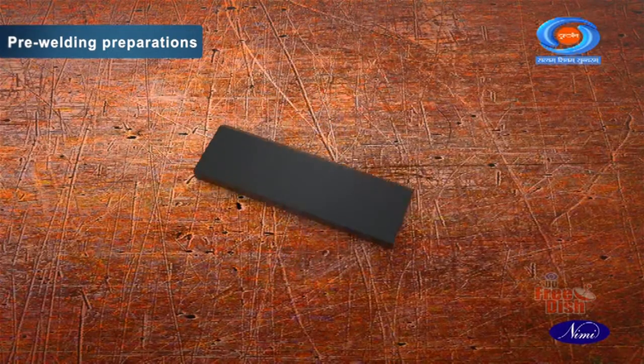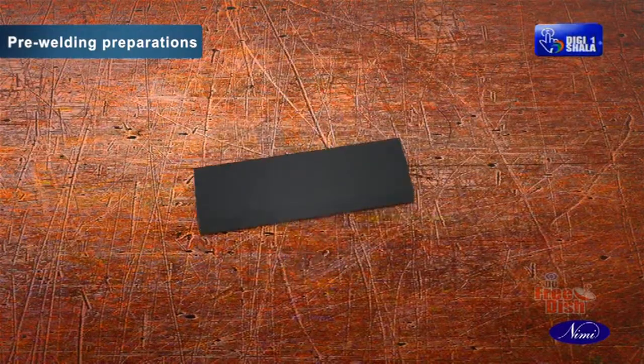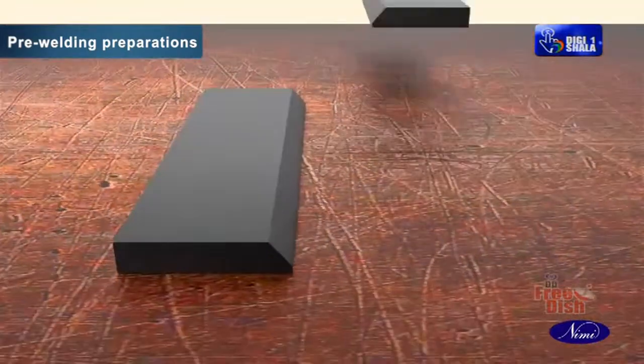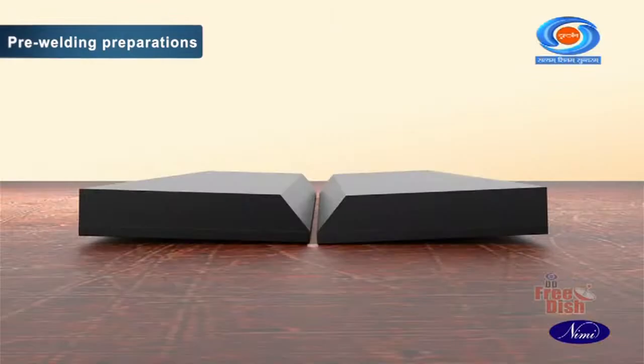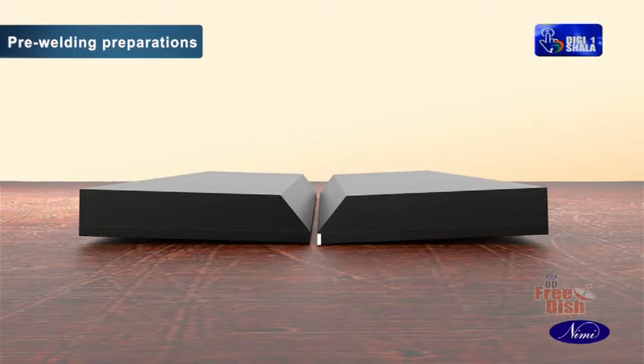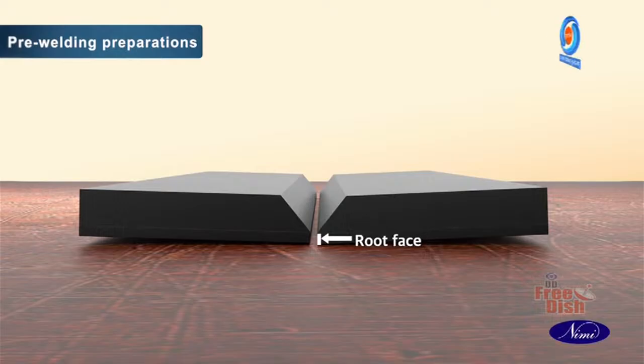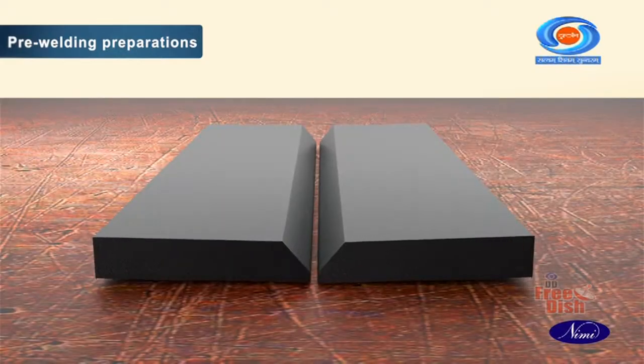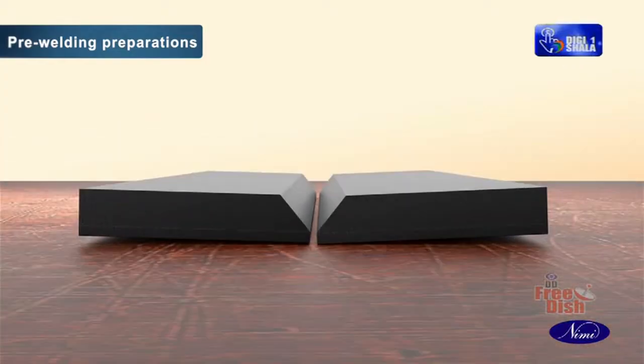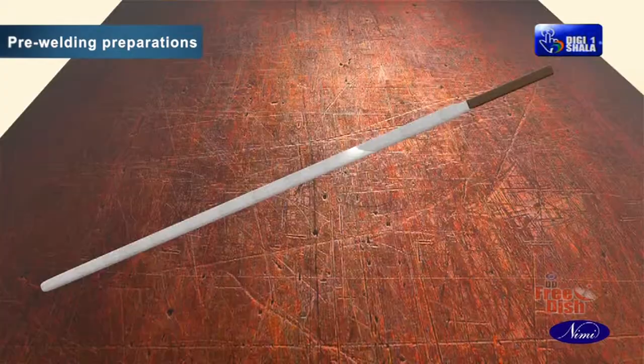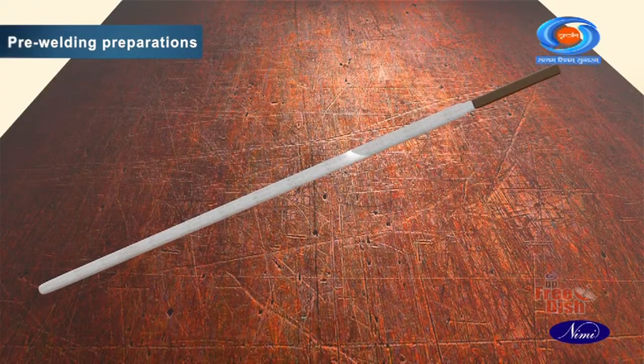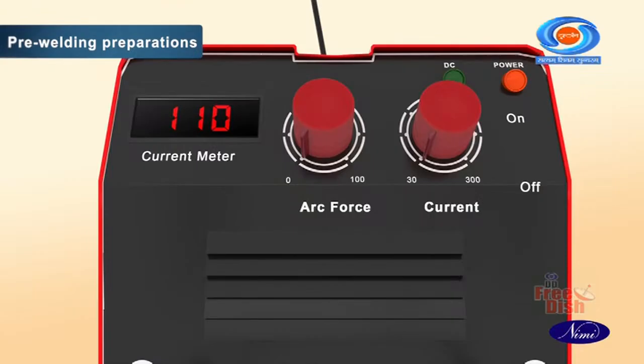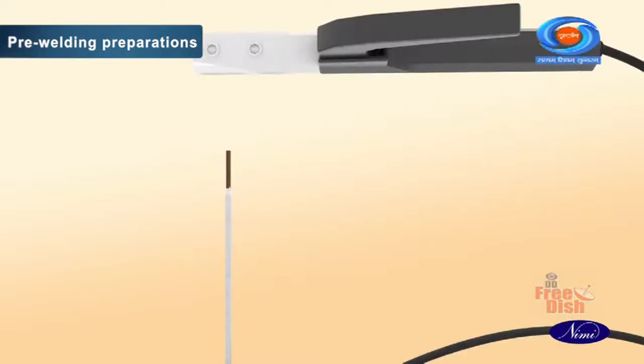Clean the plates from dirt, water, oil, grease, paint and keep the plates in line in the form of a butt joint with proper root gap. Maintain a distortion allowance of 1.5 degrees on each side of the joint. Use a 2.5 mm medium coated MS electrode and set to 110 amps current. In the case of a DC welding machine, connect the electrode cable.